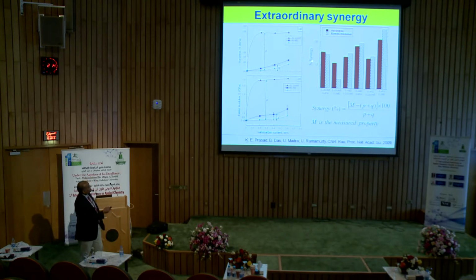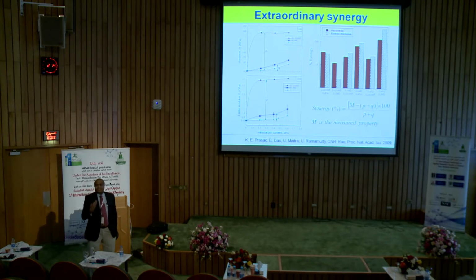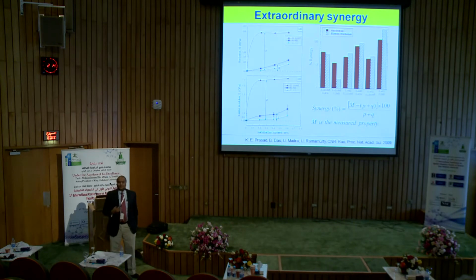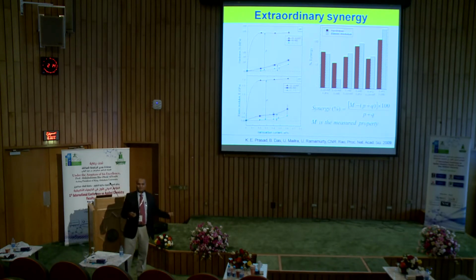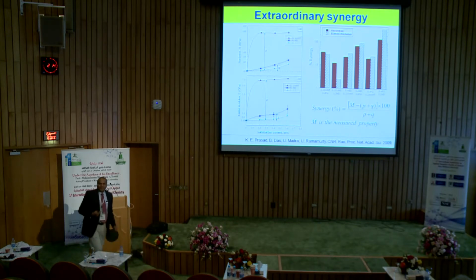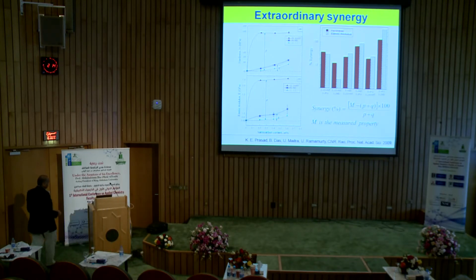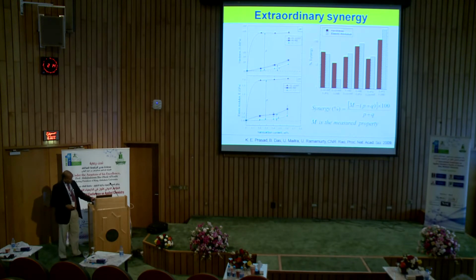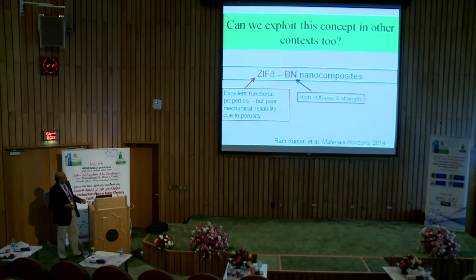So what you will see is this is a logarithmic scale. Suppose you put 0.4% graphene and 0.2% nanodiamonds, you will get an additional benefit of 400%. That's 4 times more than what you would get by just putting individual components. So this is quite a dramatic enhancement in properties. This is because of the interaction that happens and the different physical interactions that happen.